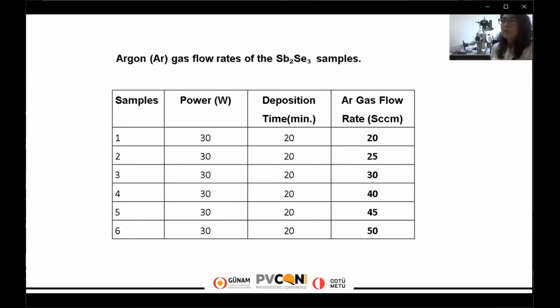Yes, in this study, antimony selenide absorber layers, as I've already said, were grown with the RF magnetron sputtering method by using different argon gas rates, starting from 20 sccm until 50 sccm. This argon gas flow rate, of course, affects the pressure in the sputter chamber. So hereby the optimum pressure for the coating adhesion and structural properties were determined. And in addition, the effects of the argon gas rate on the physical and optical properties have been investigated for use in thin film solar cells.